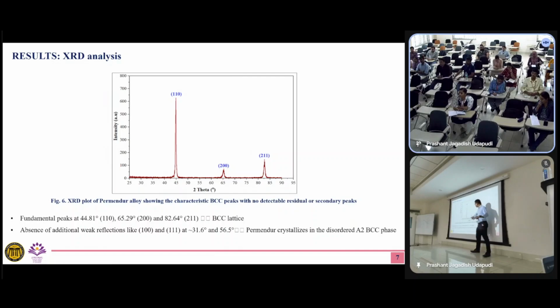Now you see how there are only 3 clean peaks. And can you tell me why we only have 3 clean peaks? Cubic structure, simple, highly symmetric structure, which is cubic, right? But if you had orthorhombic or monoclinic or hexagonal, what will happen?